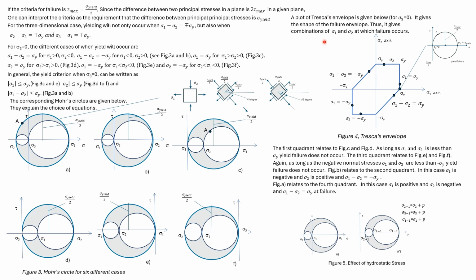One issue related to failure is the effect of hydrostatic stress. Figure 5 is shown here. Consider that apart from these stresses, the element is subjected to extra hydrostatic stress. If the hydrostatic stress is P, then the magnitude of all the principal stresses will increase by P as shown. The whole Mohr circle will move by the distance P. Since Tresca's criteria is related to the difference in the principal stresses, Tresca's criteria will not be affected.